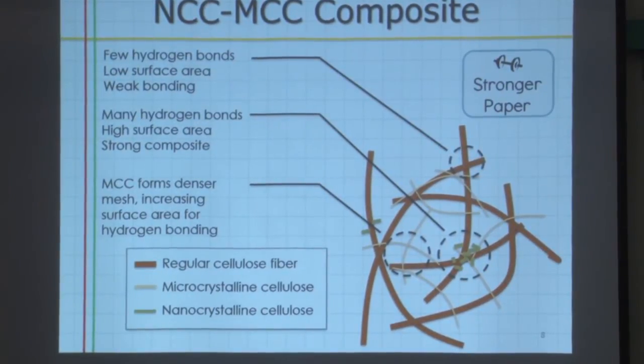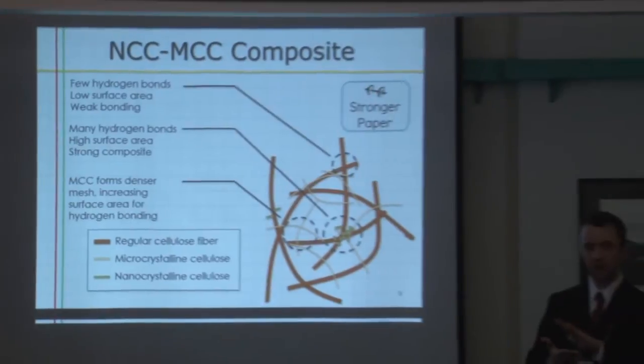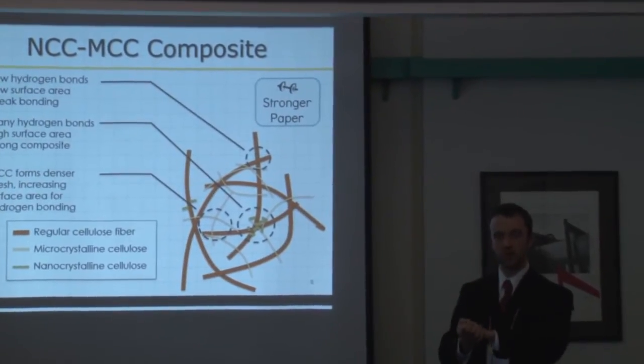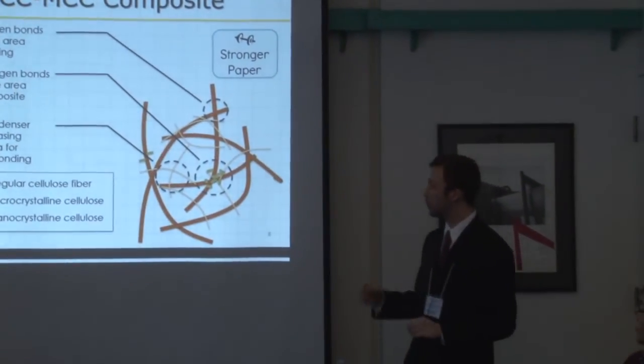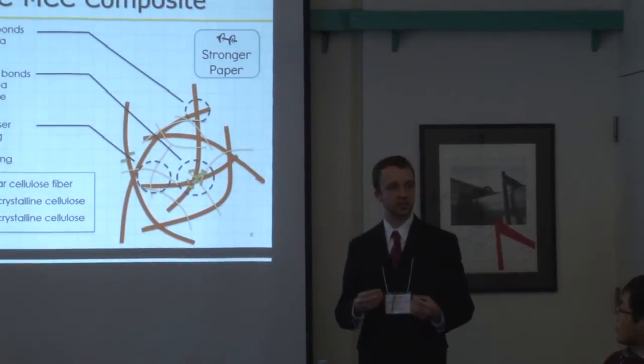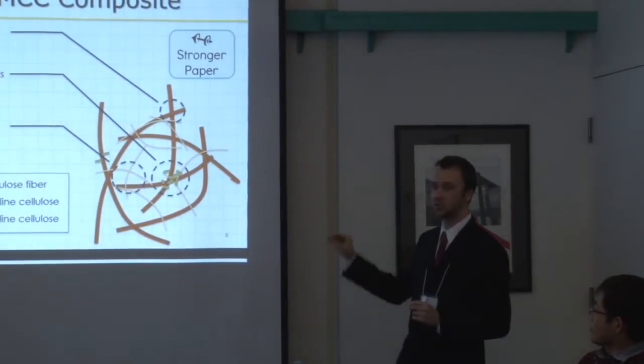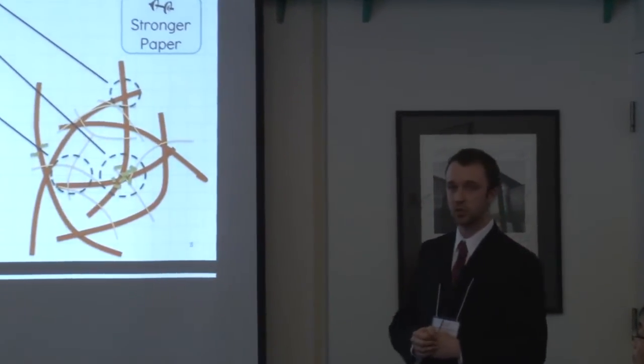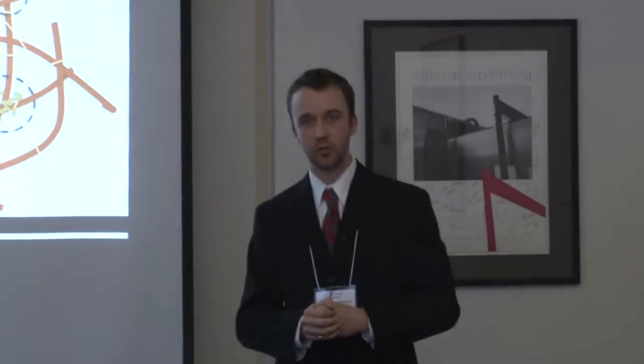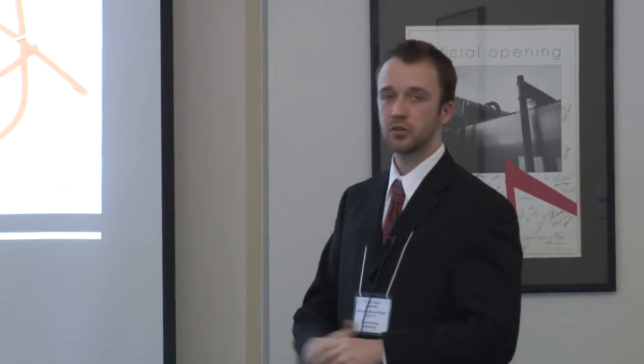Cellulose in a paper matrix is held together, among other things, by the hydrogen bonds present between the fibers when they overlap. By incorporating the nanocrystalline cellulose, it acts somewhat like an adhesive, in a sense, creating more hydrogen bonds between the fibers, increasing the strength of the material. We add microcrystalline cellulose to help bridge the size gap between the large regular cellulose fibers, creating more connection points